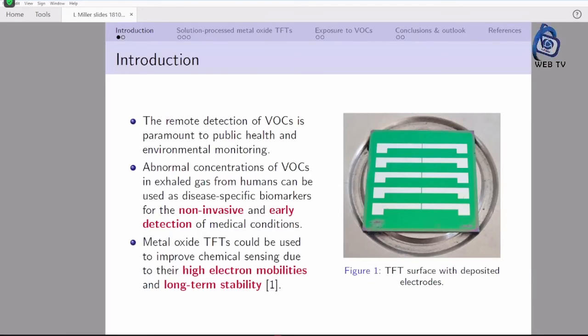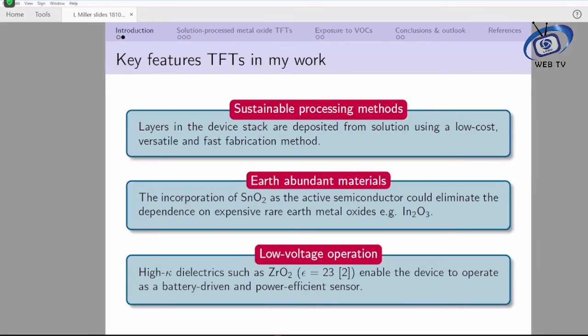The key advantages of my work include using solution processed materials, which are highly abundant. The fabrication method involves spin coating and annealing, which is simple, versatile, and thin film transistors can be manufactured in just a few hours. The operating range of the thin film transistors presented in the following slides is from -40 to 40 volts, as they are based on silicon nitride or silicon oxide as the dielectric. Therefore, I also aim to incorporate high K dielectrics such as zirconium oxide to ensure low voltage operation in the long term.